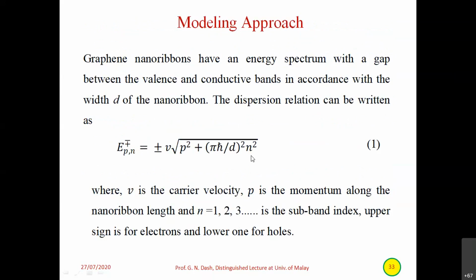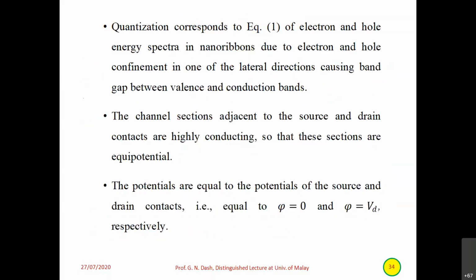Then the modeling approach proceeds via the dispersion relation, which is like this. Those who are not theoretically motivated, let's keep this, no problem. Here this energy versus wave vector relation is given. V is the velocity in graphene, which is 10 to the power 6 meter per second. With this high value, carriers in graphene flow like relativistic particles. That is why we use that theory. Quantization corresponds to equation 1 of electron and hole energy spectra in the nanoribbon due to electron and hole confinement in one of the lateral directions, causing a band gap between valence and conduction bands.